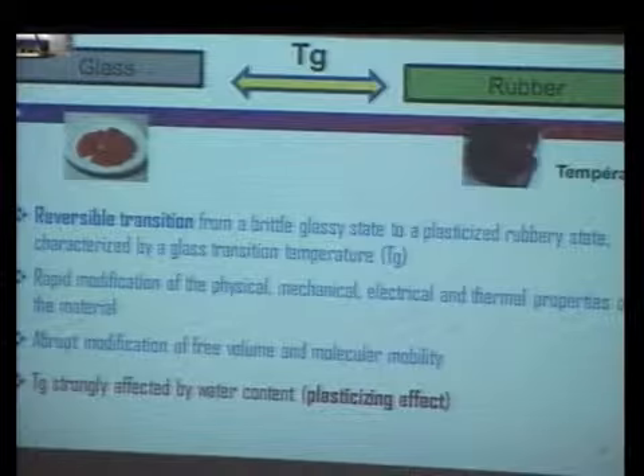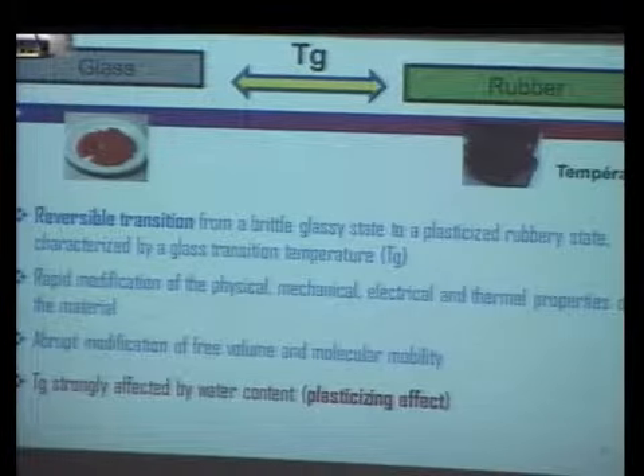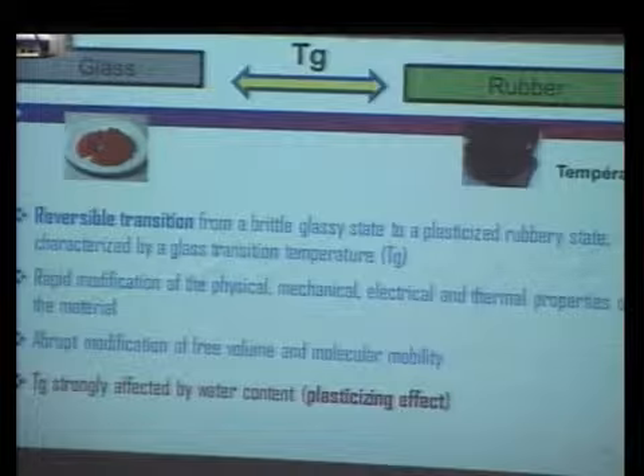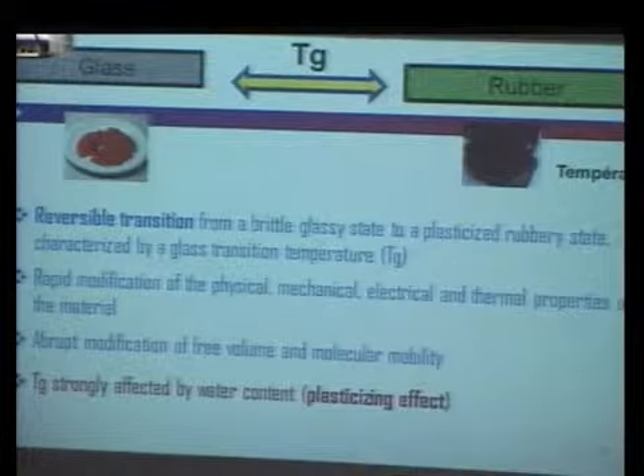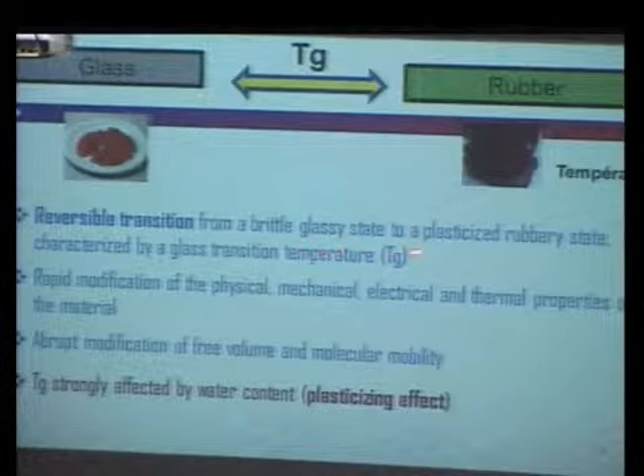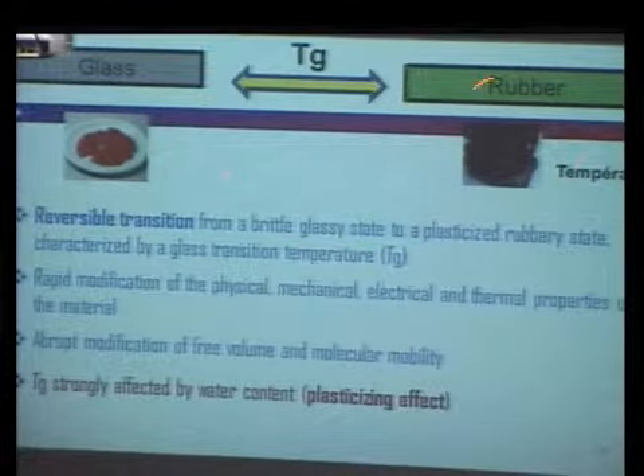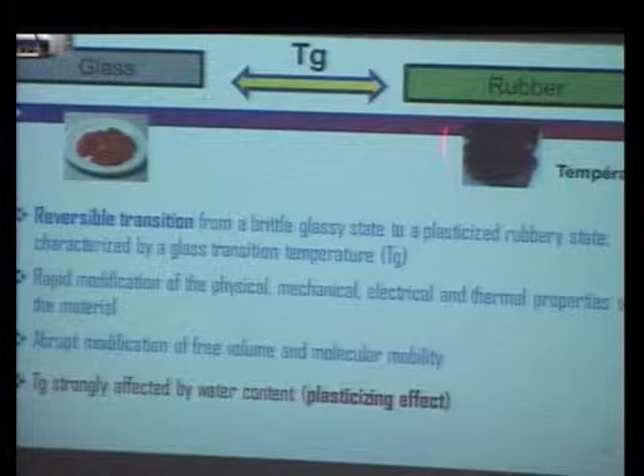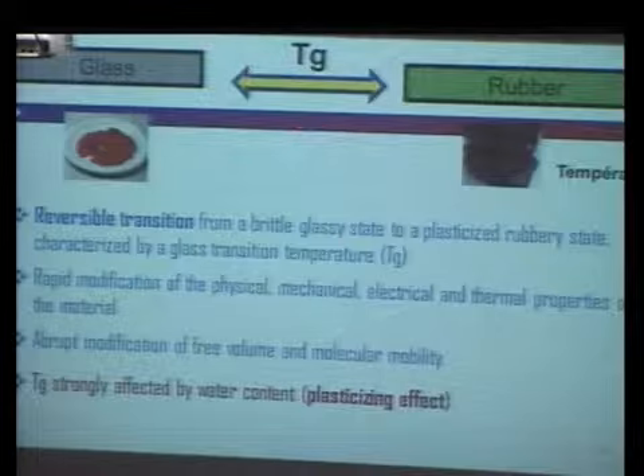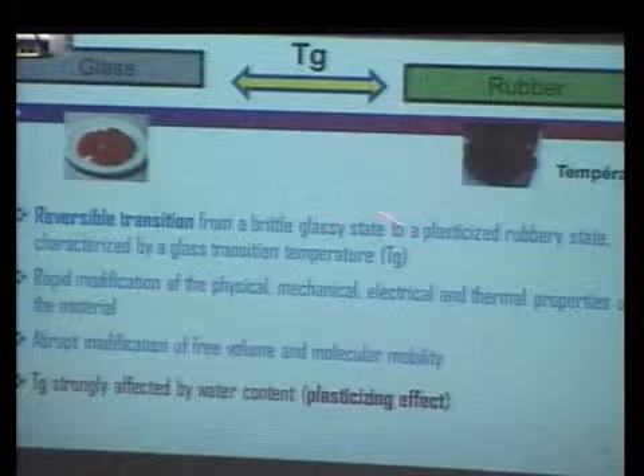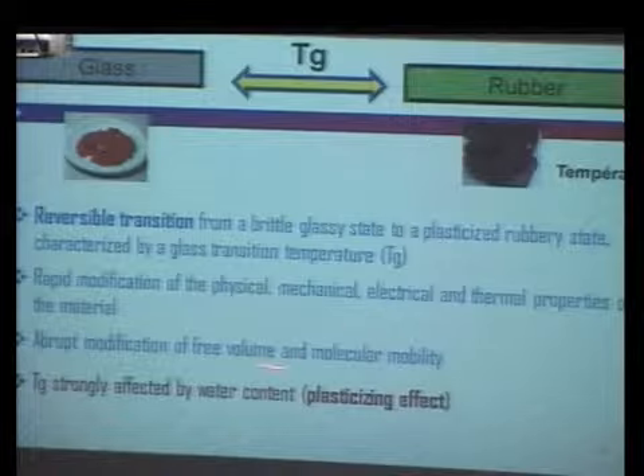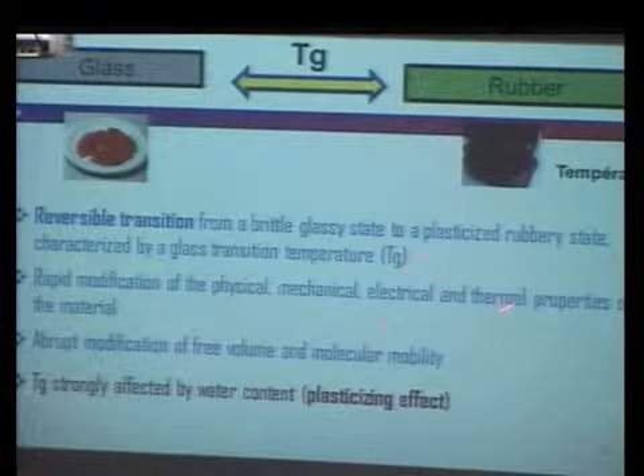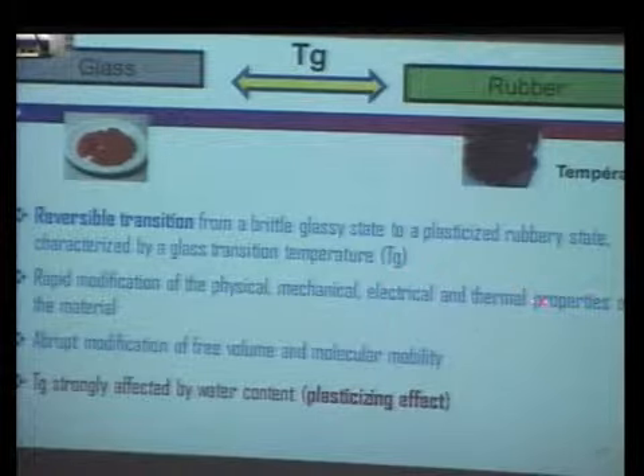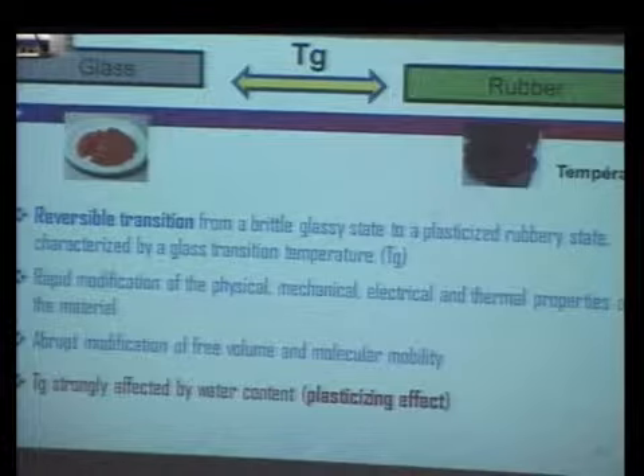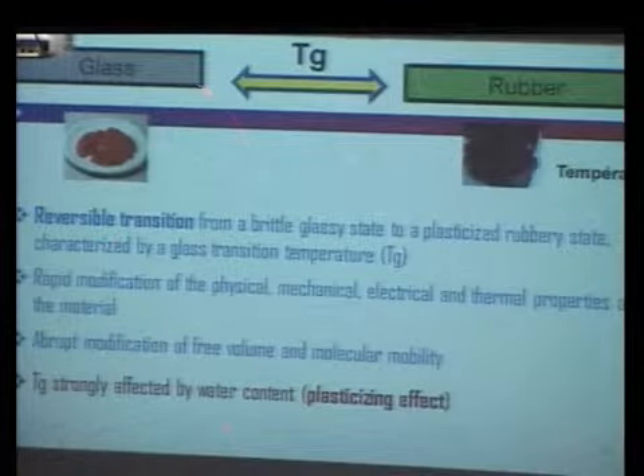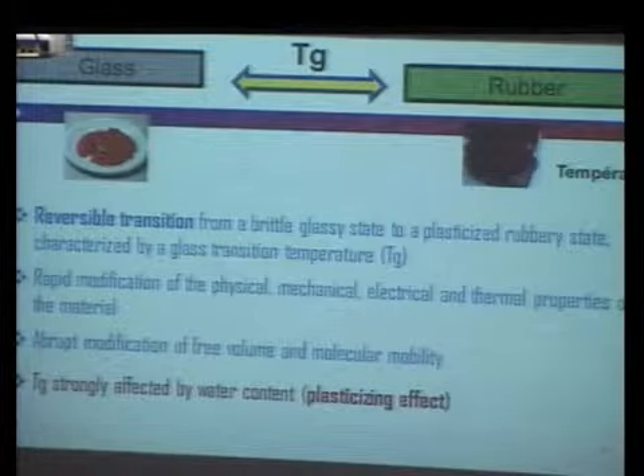Transitions of the first order are evaporation and freezing, where there is heat involved and so on. Here, there is no energy involved. It's a reversible transition from a brittle glassy state to a plasticized rubbery state. This transition is characterized by a temperature, and there is a rapid modification of the physical, mechanical, electrical, and thermal properties of your product. There is an abrupt modification of free volume and so on. And as I told you, this temperature is strongly affected by water content.